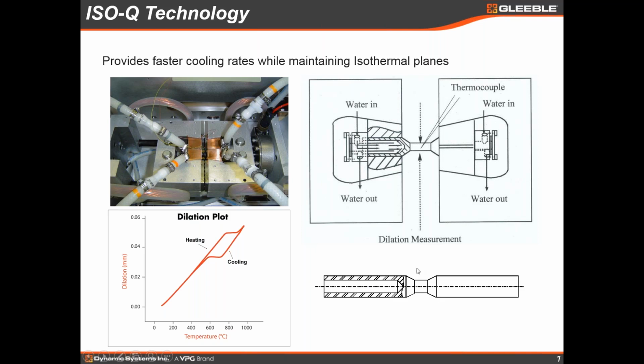So again, similar to when we have this clamped in copper water-cooled jaws, we get a very, very fast heat extraction rate from the ends of the sample. But again, the heat flow is almost entirely axially through the sample, which means we can get very, very fast cooling rates, while again measuring dilation in the diametral direction in the center of the sample, where we keep an isothermal plane, surface to center to surface, so we can get very sharp dilation curves, and we can get very good temperature readings of where these transformations occur.